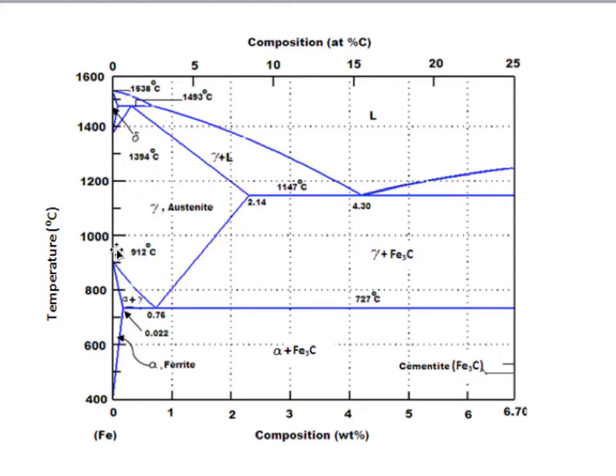But if you look down here, we see ferrite. That's the opposite. The crystal structure in ferrite, with its body-centered cubic, cannot dissolve much carbon. Actually, the maximum solubility of carbon is 0.022, and it occurs here. It's even smaller at other temperatures. So here we cannot put in so much carbon, and that's a very important thing here, how carbon is distributed between the austenite and ferrite during the different transformations occurring in this region.